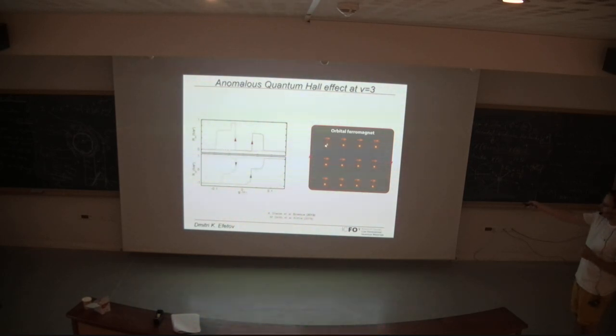But again, in this case, the picture which is basically addressed at this point by some theorists is that it could be an orbital ferromagnet, because in graphene spin orbit coupling is weak. Nobody ever observed magnetism in graphene from the carbon lattice, etc. So it must be some sort of more exotic ferromagnet. But flat bands are often sufficient. So this is why you don't see it in usual graphene. There is ferromagnetism in usual graphene, but then it's induced by the magnetic field, in the sense that you form the zero energy Landau levels. So you have a large density. Okay, yeah. And here it seems to be the flat band that replaces this.